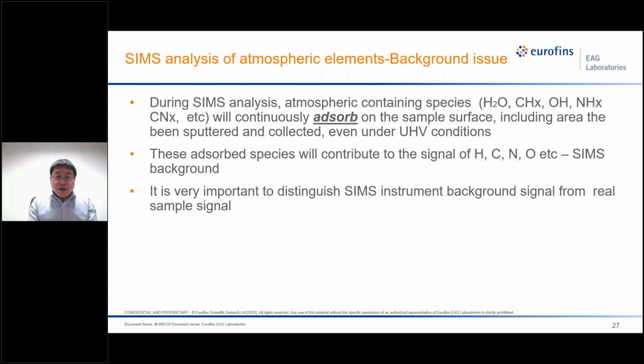So where do the backgrounds come from? During the SIMS analysis, atmospheric species such as H2O, CHx, OH, NH, CN will continue to adsorb on the sample surface, including the area that's being sputtered and collected, even under UHV condition. These adsorbed species will contribute to the signal of hydrogen, carbon, nitrogen, oxygen. This is the SIMS background. It's very important to distinguish the SIMS instrument background signal from the real sample signal.